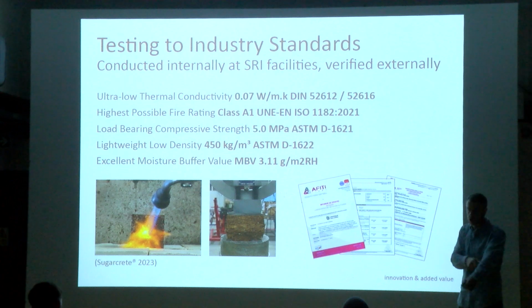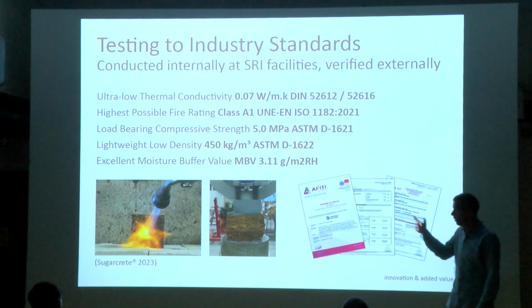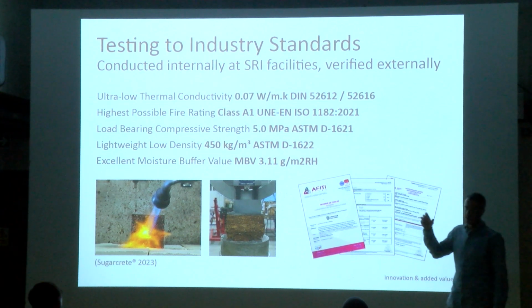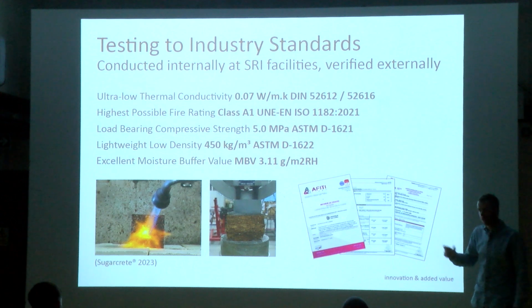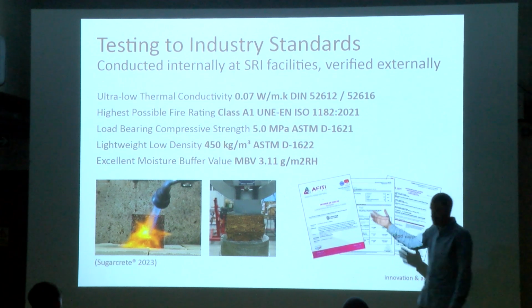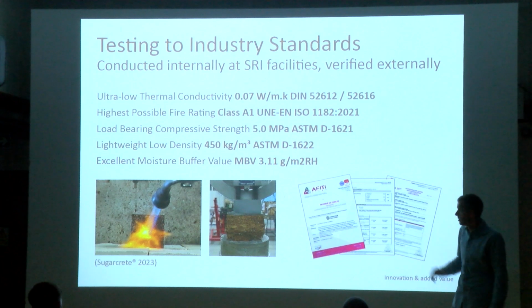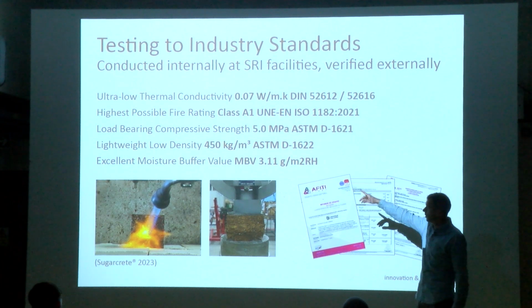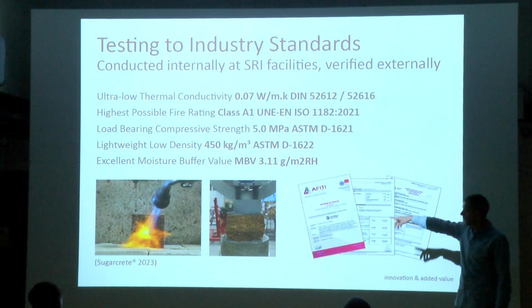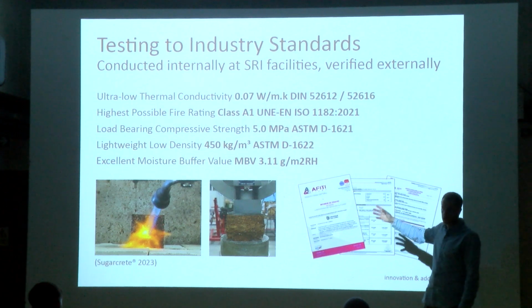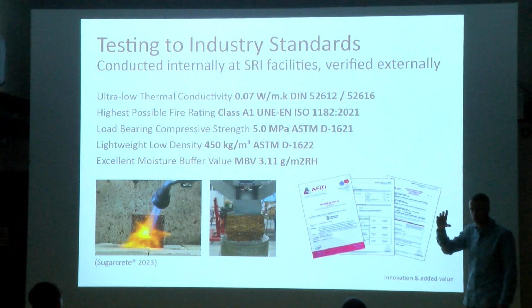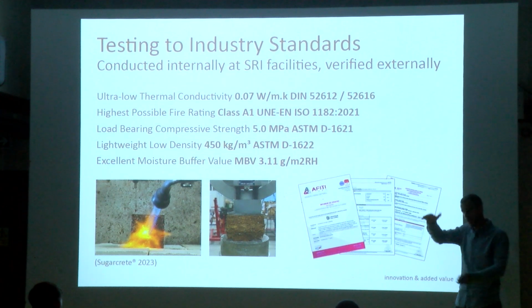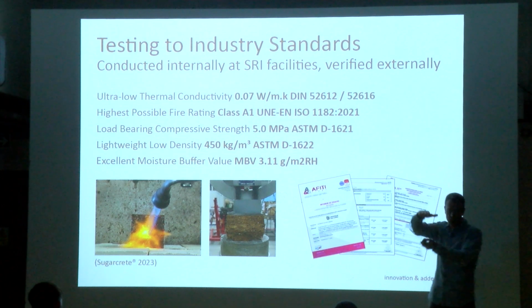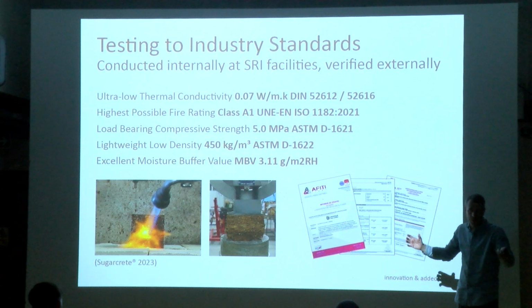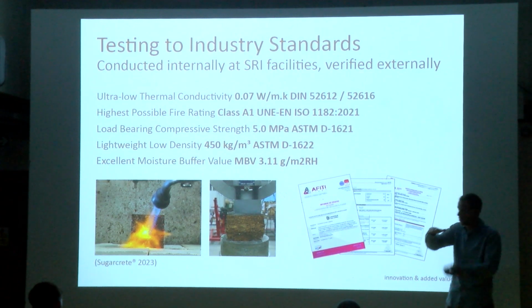So that PhD position that we are advertising at the moment will be looking into how the standards and the testing that we have in industry at the moment will need to adapt to somehow make the most of what biomaterials offer. For instance, on the compressive strength, biomaterials, unlike concrete blocks, have very good residual strength, which means that if you have a block of concrete and you crush it, once it breaks, it crumbles and there is nothing left in terms of strength.